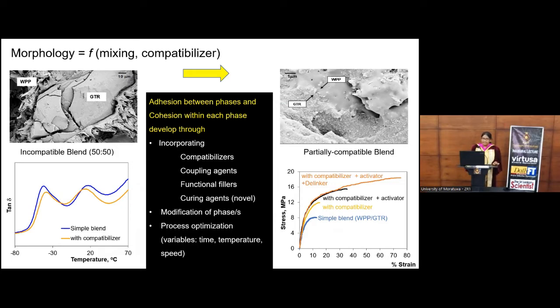In an incompatible blend, the SEM images show a gap between the two phases. During stretching, the two phases separate and voids are created, and we can easily see a phase separation. But in a partially compatible blend, the two phases overlap and there is no separation. To enhance the properties of a blend, we have to incorporate different types of additives that will enhance the adhesion between phases, or enhance the cohesion within each phase.